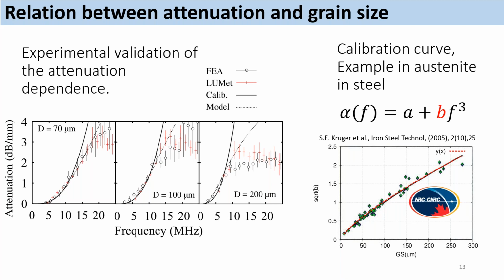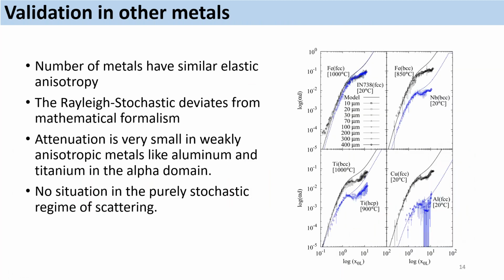Since then, a number of other calibrations have been constructed in other metals, but this simple relationship between attenuation and B, which is a function of grain size, is usually well established. So I just want to show you here what happened in other metals. Like I said, we have developed a calibration for austenite, which is the iron FCC here. And I want to show that this type of relationship applies to other metals like titanium, copper, aluminum, and niobium, among others. Here is a nickel-based superalloy.